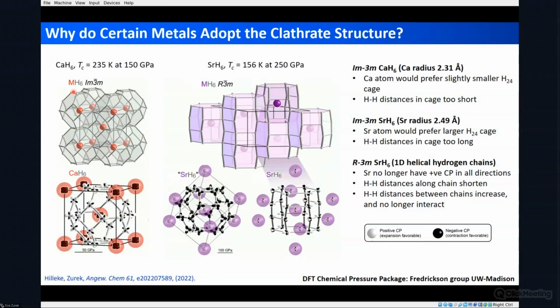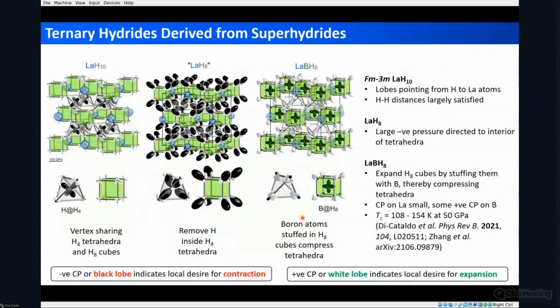So these three-dimensional cages distort into these types of one-dimensional chains, and because of that, TC is lower. And obviously, this is going to be a size effect, which is what we found. The SrH6 is somewhat going to be too large for this type of a cage, and this type of a distortion is preferred. But going on to the ternary hydrides, how could we design these types of ternary hydrides using the chemical pressure map idea?